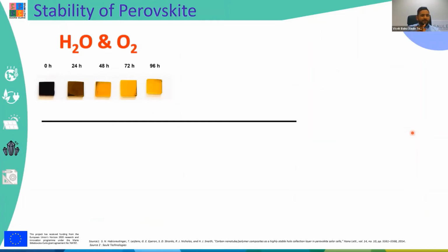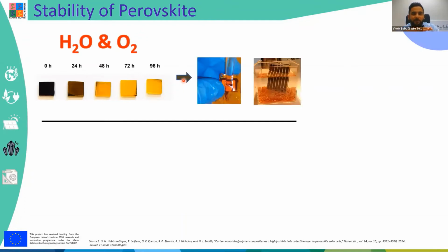And unfortunately, perovskite can get degraded in the presence of moisture or oxygen, like you can see. Over the hours, you see this perovskite, which had photovoltaic properties, get degraded and form this yellow phase, which is non-photovoltaic. So what we can do is coat a hydrophobic surface on it, or have a proper encapsulation, which can prevent water or moisture from entering inside. Here you can see an image of a perovskite module inside a box of water. So you can see it can withstand these external degradation factors.